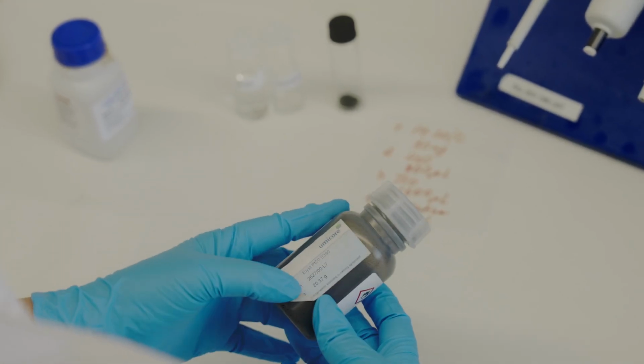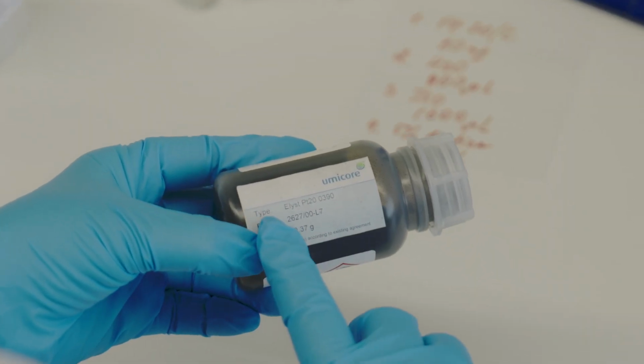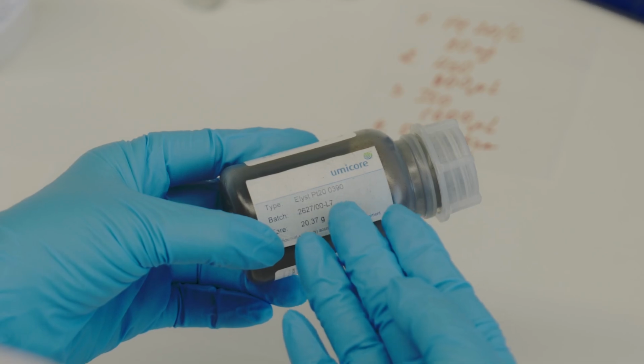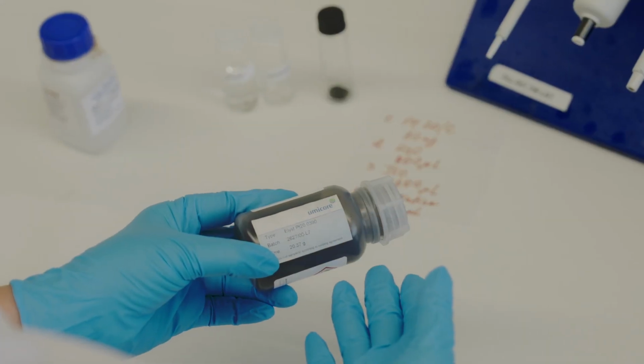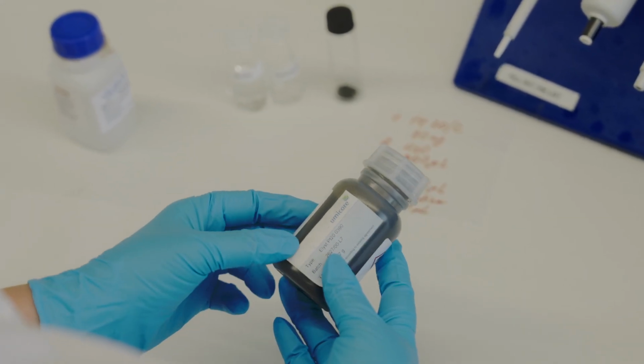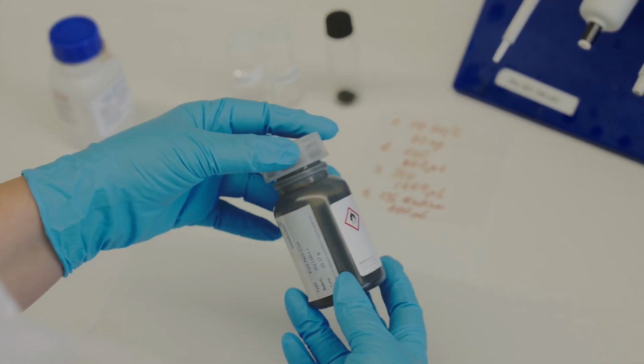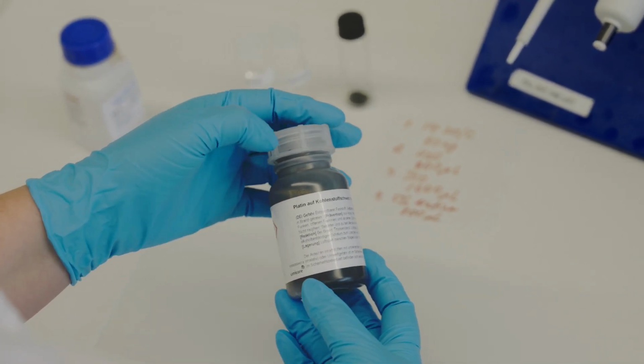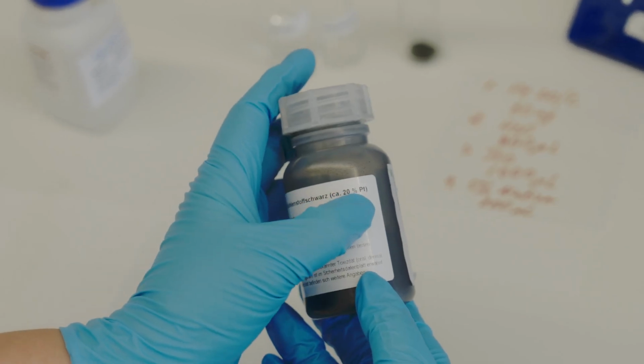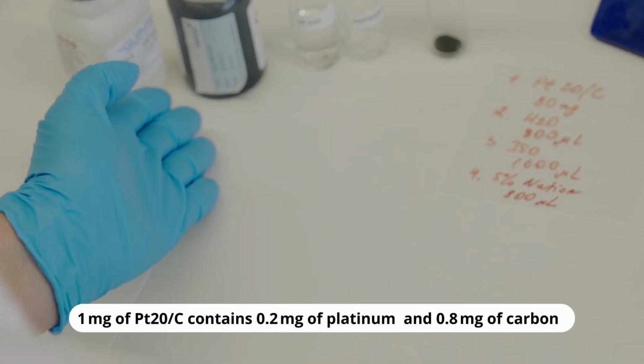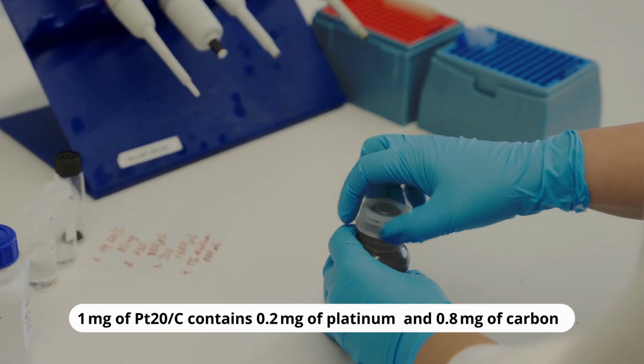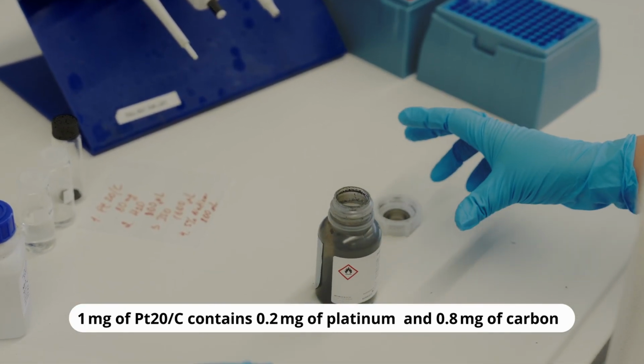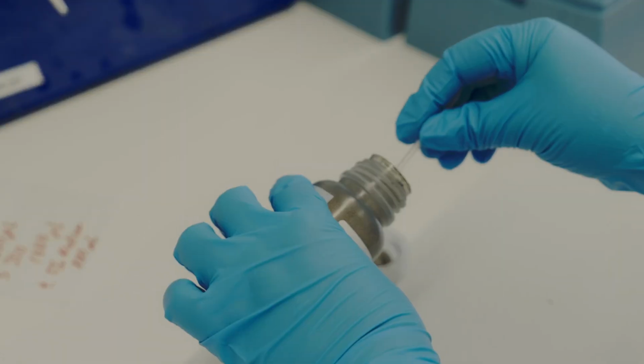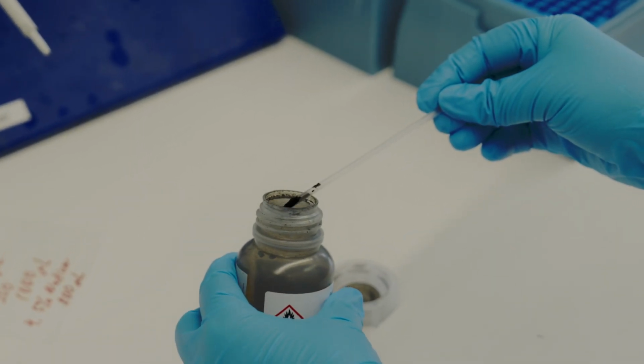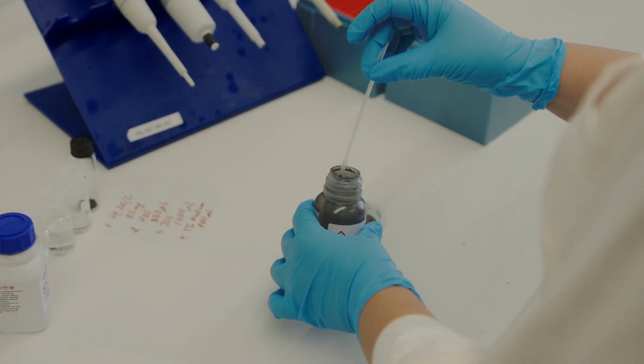Second component, catalyst material. An example of catalytic material is PT20, a dispersion of platinum nanoparticles on carbon support. The label PT20 indicates that the material contains 20 weight % of platinum. So, 1 mg of PT20 on C contains 0.2 mg of platinum and 0.8 mg of carbon. Let's take a closer look at what the catalytic material looks like.